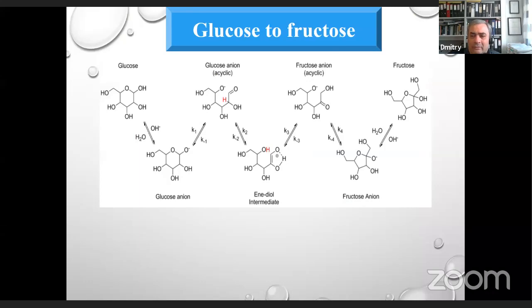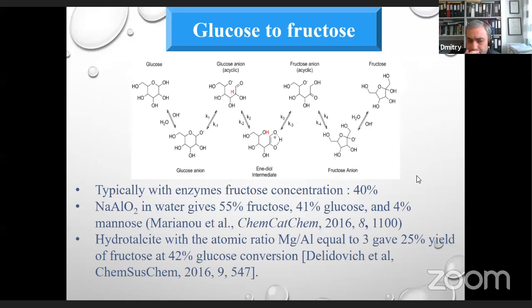So this is the reaction of glucose to fructose. It requires several steps, as we can see, and we need to have a base catalyst for that. Typically with enzymes, the fructose concentration will not be that high, 40, maybe 50%. Sodium aluminate in water gave 55% of fructose. Then there were also experiments done with hydrotalcites. The yield of fructose was 25%.